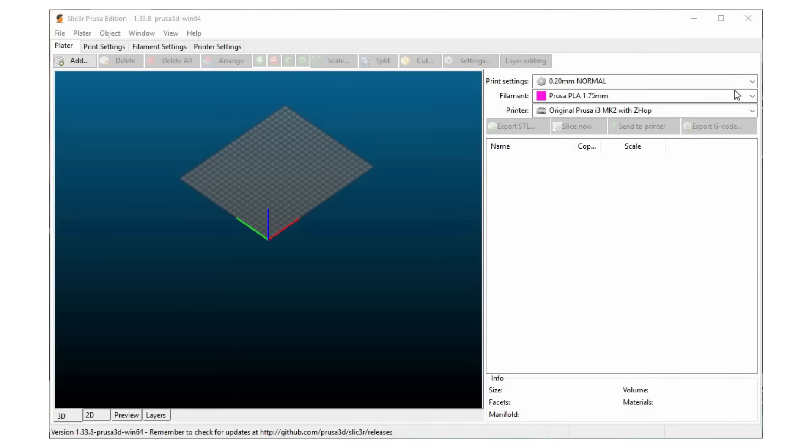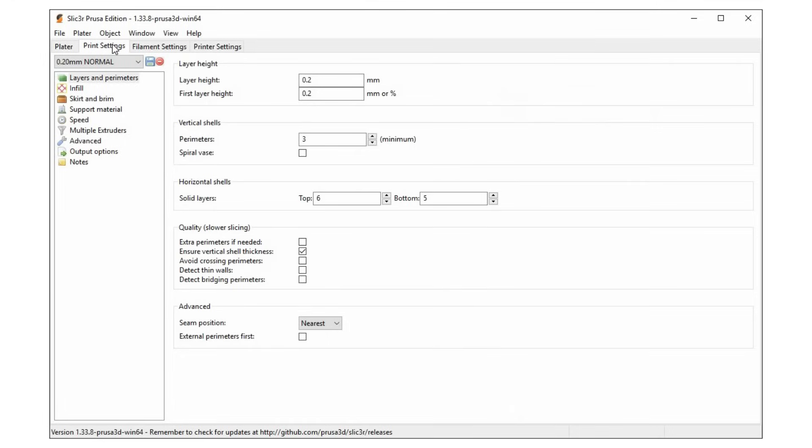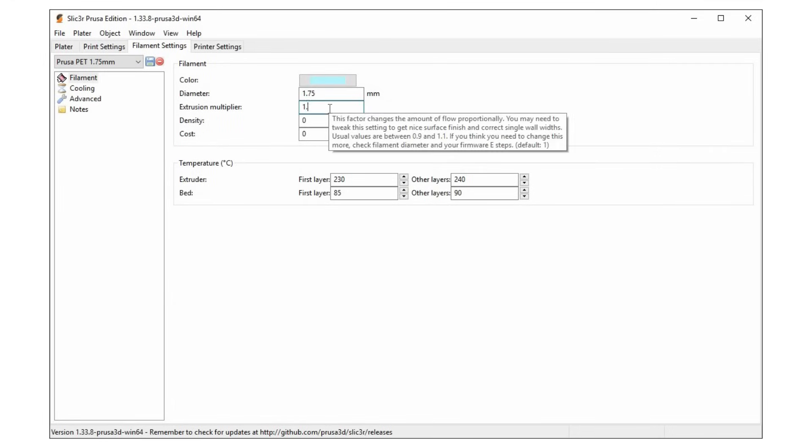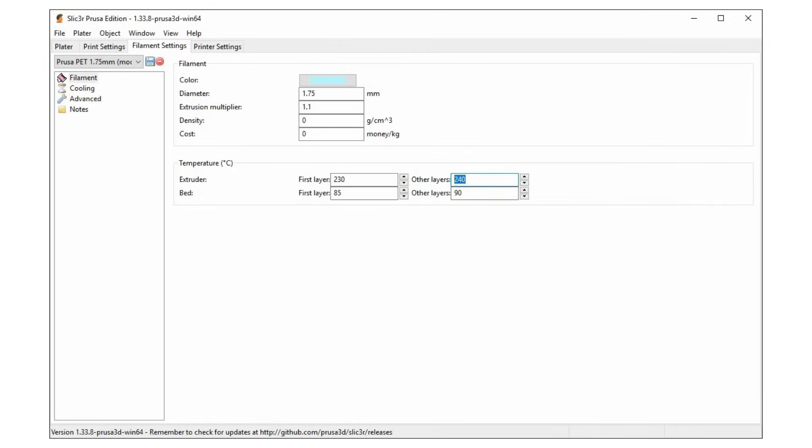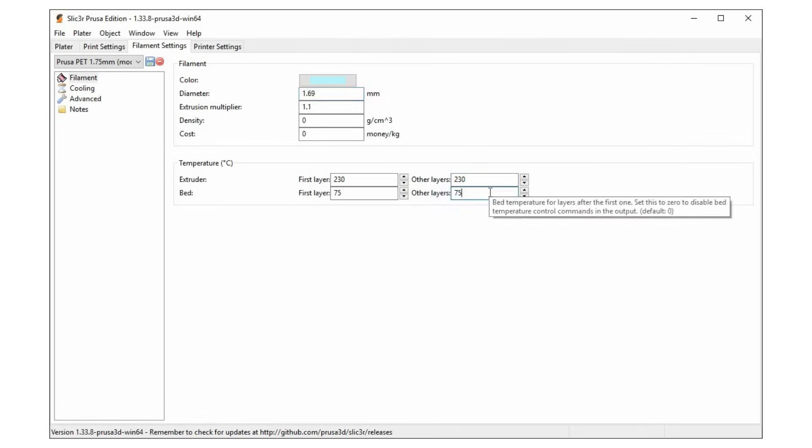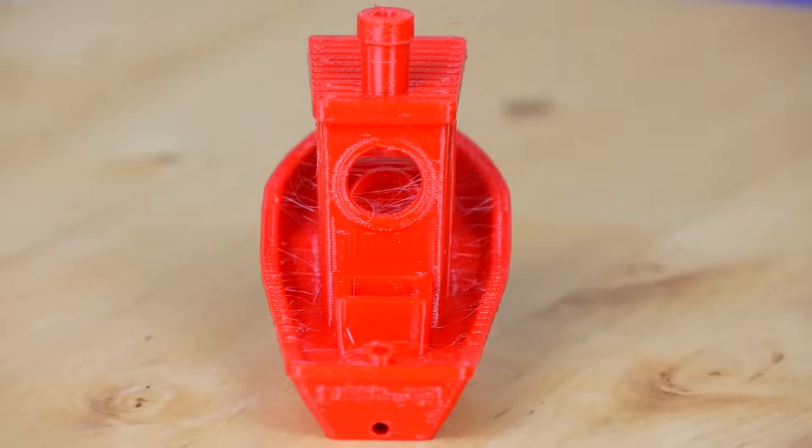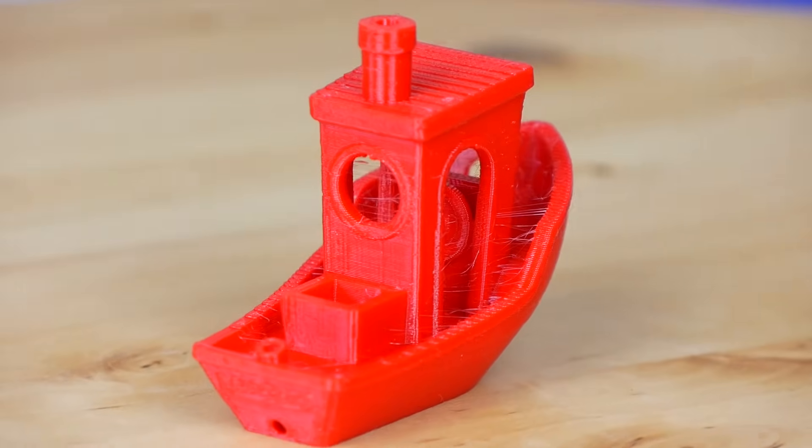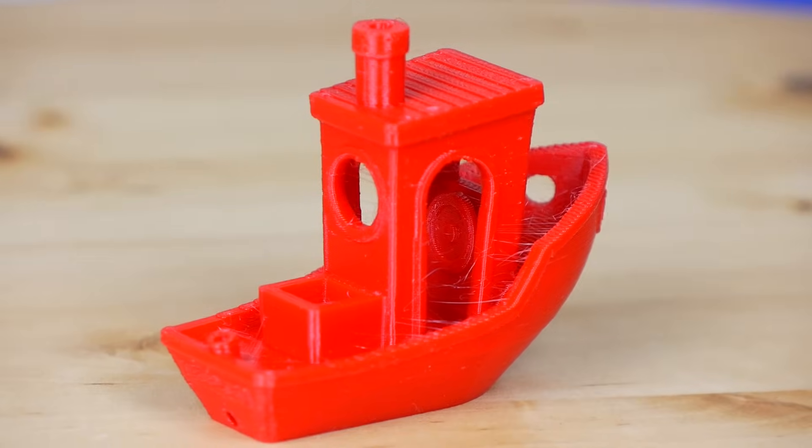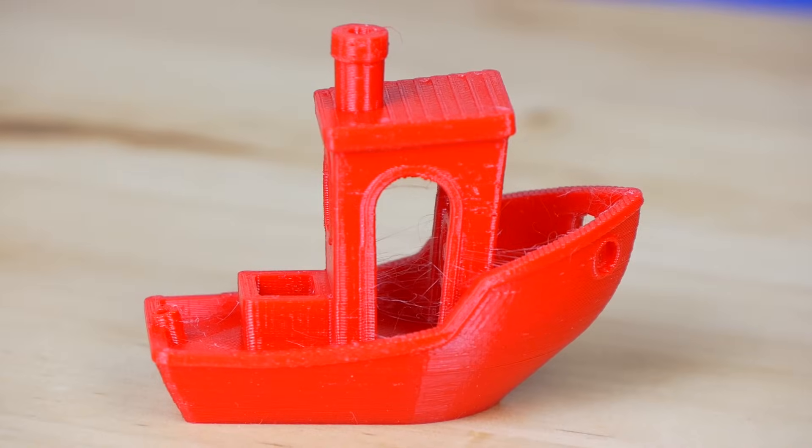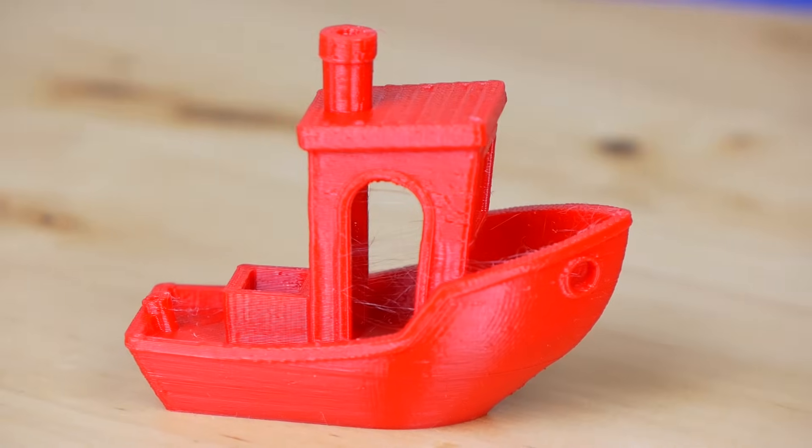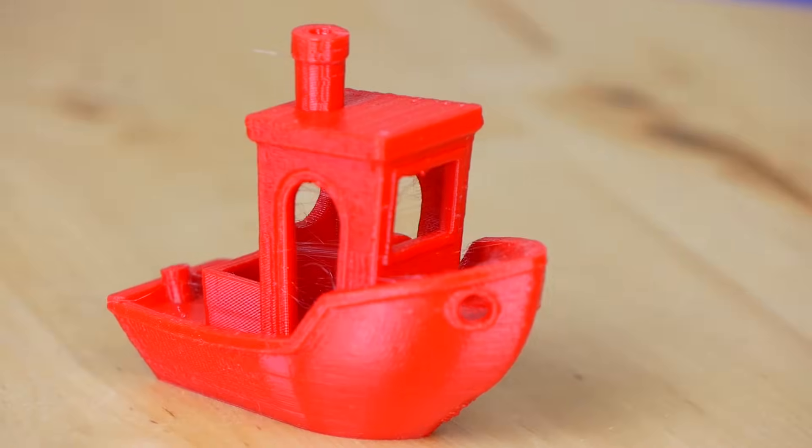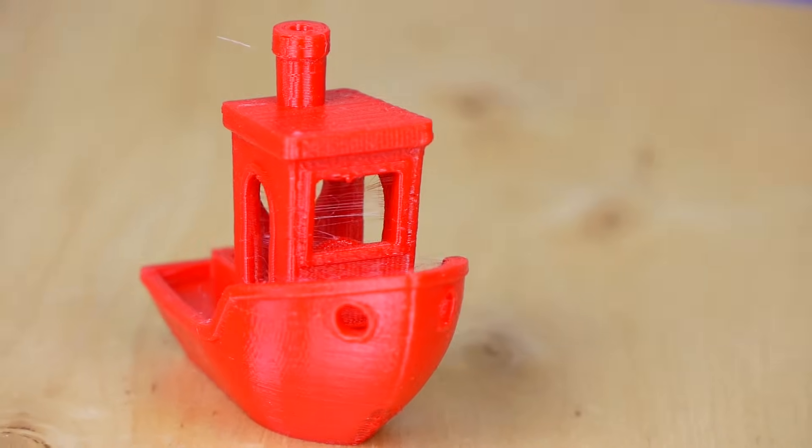This is the value which you will put in your slicer together with the measured diameter of your filament. If you don't have a very exotic 3D printer, there should be plenty of profiles on the internet or even provided for your printer and your material type. I used the Prusa PETG profile in the slicer and only added extrusion multiplier, filament diameter and the temperatures. I printed the first parts with these settings and fine-tuned the extrusion multiplier to end up with a really nice print result. From my experience PETG likes to be under-extruded just a tiny bit. The only real quality difference to PLA is the slight stringiness which could be further optimized and the worse performance in overhangs.